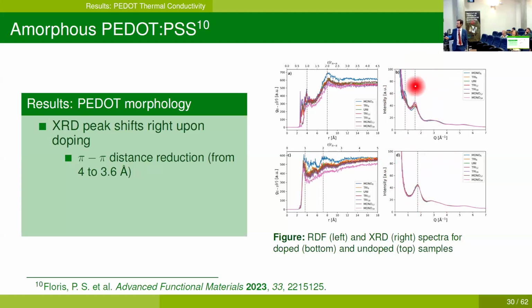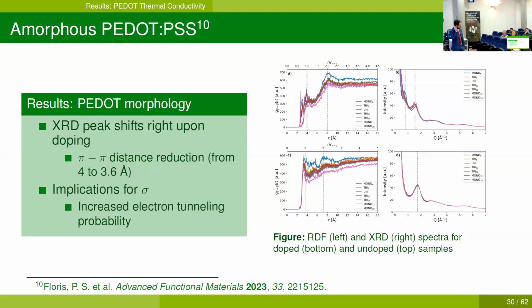patterns, and we see that on top we have the PEDOT undoped samples, and on the bottom we have the doped samples. So this peak right here corresponds to a pi distance of 4 angstroms, whereas down here it has shifted to the right, which means that it corresponds to a pi distance of 3.6 angstrom. So we can conclude that doping is responsible for a pi distance reduction from 4 to 3.6 angstrom. This does not appear to have any implication for thermal conductivity, but it probably does for electrical conductivity, since reduced pi distance also means increased tunneling probability.